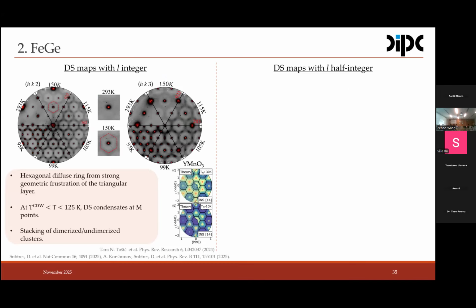So since we don't see such strong correlations in the ARPES and DFT calculations, we actually want to understand what's the origin of the charge density wave in the iron germanium. So we do the same trick. We put the sample in diffuse scattering, at room temperature, in the HK2 plane, which corresponds to the M point, or maps the M, K, gamma, M, K plane.